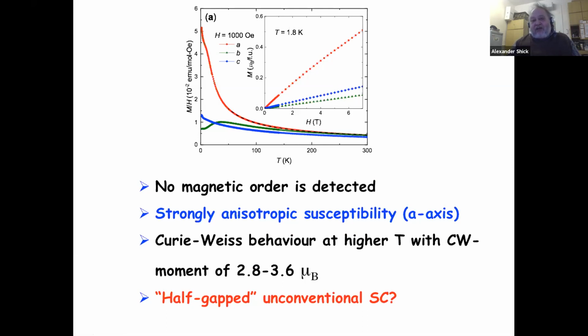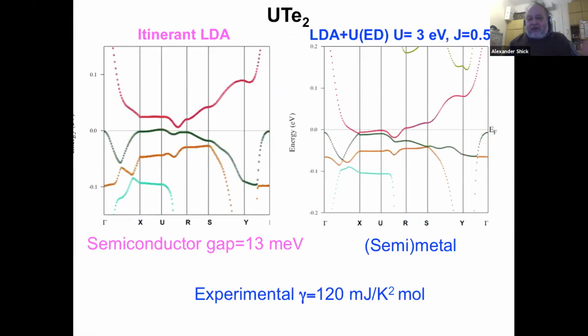It seemed to me a little bit meaningless these days, when it is clear that there is really no such phenomenon. So the first thing to do indeed is to look at the electronic structure. And when we do the conventional density functional theory, we did it, some other people did it, and including the spin orbit coupling, everything, it comes to the end that the material is actually semiconducting with a small semiconductor gap of, like I wrote here, 13, but different calculations differ from 10 to 15 milli-electron-volts.